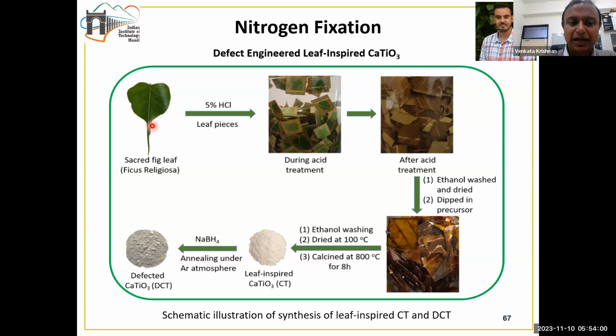We have taken a plant leaf, the sacred fig leaf, Ficus religiosa, but you can take any plant leaf and then do some sort of treatment and finally prepare a leaf-inspired calcium titanate material. This is a material which has the micro and nanostructures of the leaf embedded on it. Then we can introduce certain defects onto this material. The defects are oxygen vacancy defects, and these defects have high charge localization, which are selectively distributed across the catalyst.